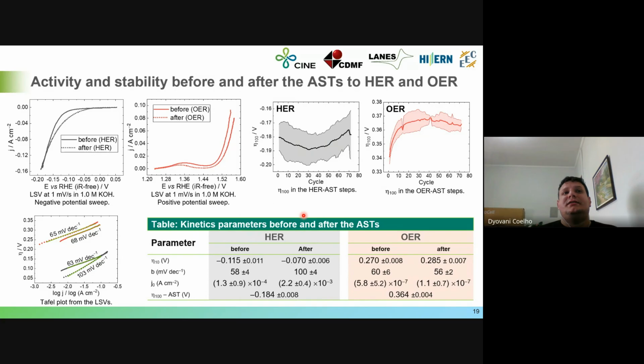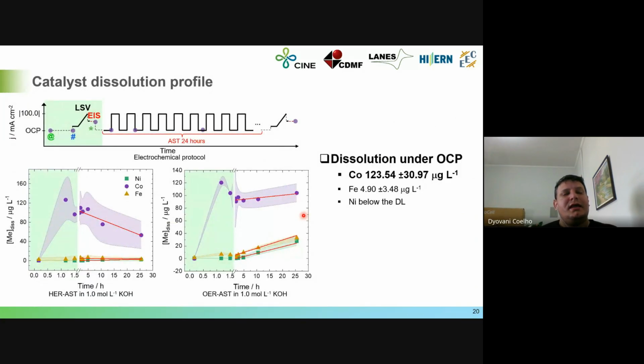But what is happening with the metals in the electrolyte? As you can see here, in the electrolyte, we have a catalyst dissolution. The main catalyst dissolution happens during the open circuit potential. So in the first part of the electrochemical protocol, we can see the main catalyst degradation. And the metal that is dissolved during this step is the cobalt. The iron and nickel are really tiny, which means that iron and nickel are stable in this kind of condition.